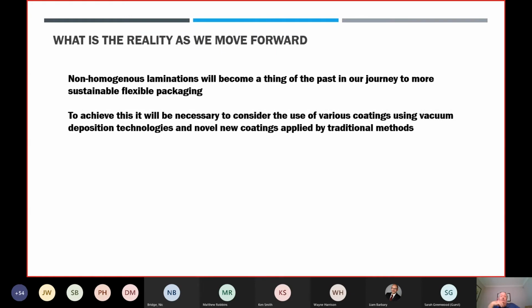And to achieve what these companies want, there's going to have to be various coatings used, vacuum deposition technologies and new novel coatings. And also you're going to have to look at the fact that people are going to have to develop these new films. You know, a more heat stable polypropylene. Currently working with a polypropylene that's pretty well heat stable up to about 160 degrees centigrade. Typically it would be about 130 degrees and it would start distorting and shrinking and doing all those sorts of things. So people are working towards that.